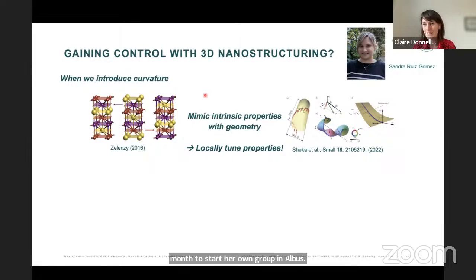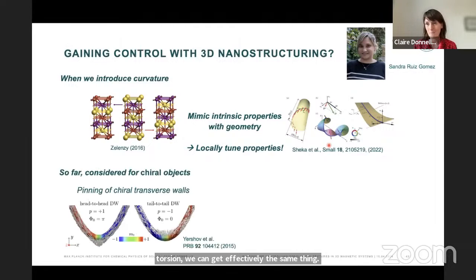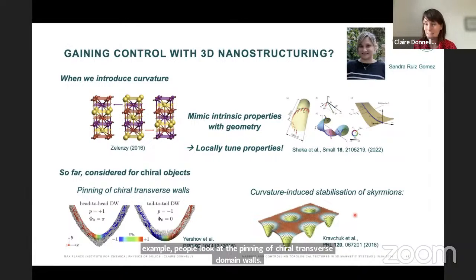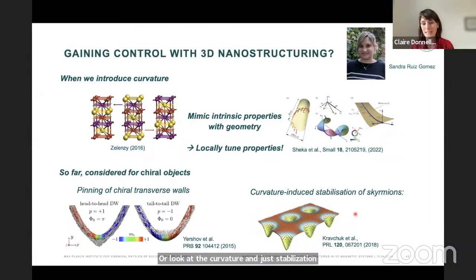The idea that we are exploring here is symmetry breaking. We're very used to breaking symmetry in the unit cell and introducing the Dzyaloshinskii-Moriya interaction, or if we have, let's say, asymmetric stacks. But what we can now see is that if we introduce curvature or torsion, we can get effectively the same thing. There's already been a number of works where people use this phenomenon to change the energy landscape of chiral objects. For example, people look at the pinning of chiral transverse domain walls, or the curvature-induced stabilization of skyrmions, as I mentioned a few slides back.